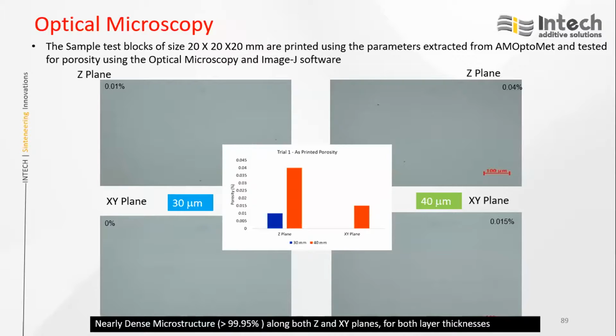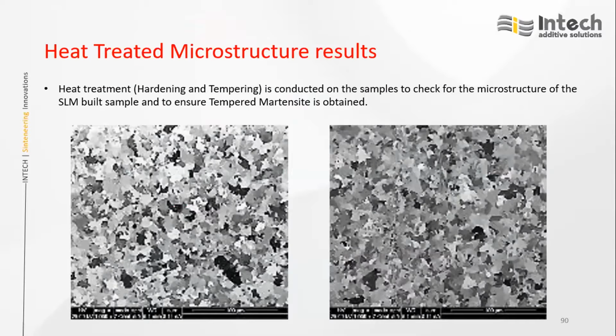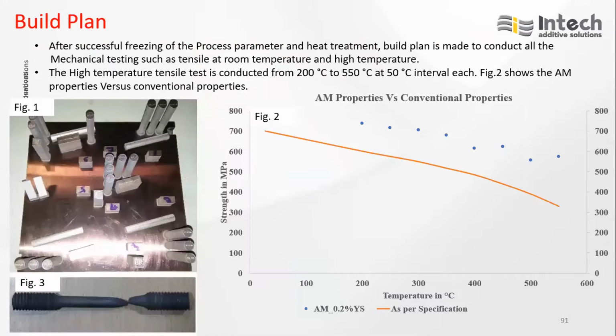So finally we took 40 microns for actual printing, and heat treatments were optimized. The requirement is a tempered martensite structure. To achieve that, many heat treatment cycles were applied, and finally the heat treatment cycle was also optimized. This work was carried out by the Indian Institute of Science.